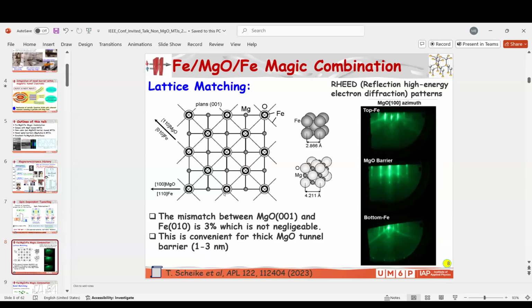But I will go through it also. So the first magic combination, the aspect of this magic combination is the lattice match. Easy, we can do it easily. Iron, we are limited somehow to iron. This is also an inconvenience, and the lattice match is 3%. This will introduce some dislocations, misfits, and so on.